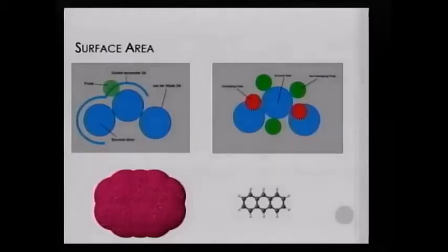For example, you want to use 3.72, so you take half that, plus the van der Waals radius, and using an algorithm, you put it over the surface of this sphere that has the radius of the probe plus the van der Waals radius, in a random position. So for each atom, for example, you can place up to 10,000 probes per atom. So you can get a very distinct, here it's a little bit difficult to see, a very distinct vision of how much each atom contributes to the surface of the entire system, for example.